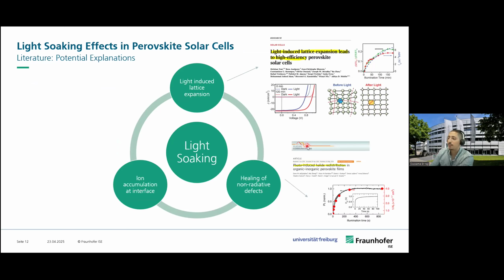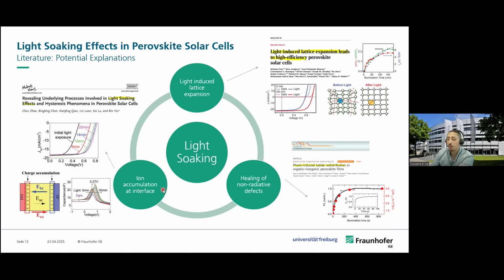Other researchers have found another reason, which is healing of non-radiative defects, where under illumination time, the density of defects was reduced, which can be reflected here in an increase of PL intensity, which then also matched well with the increase in VOC. And the third reason, which was put forward in literature, is that of ion accumulation at the interface.